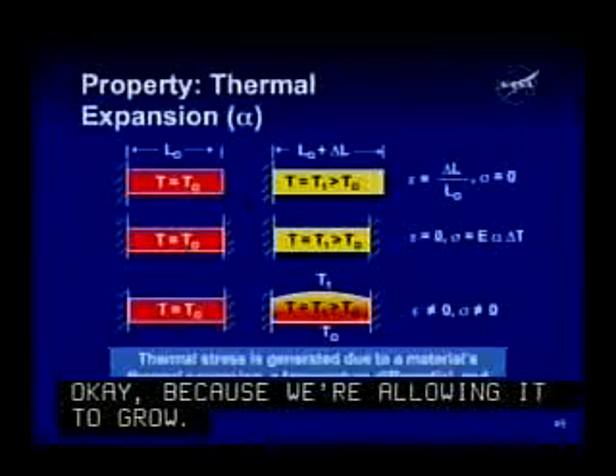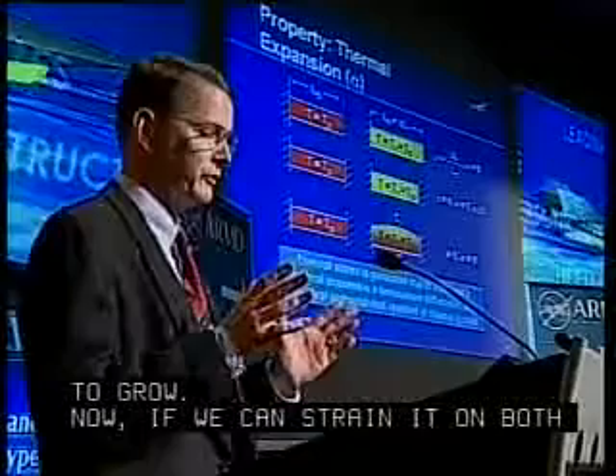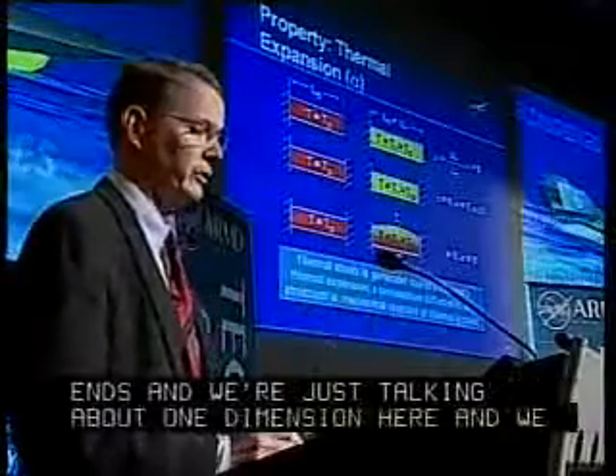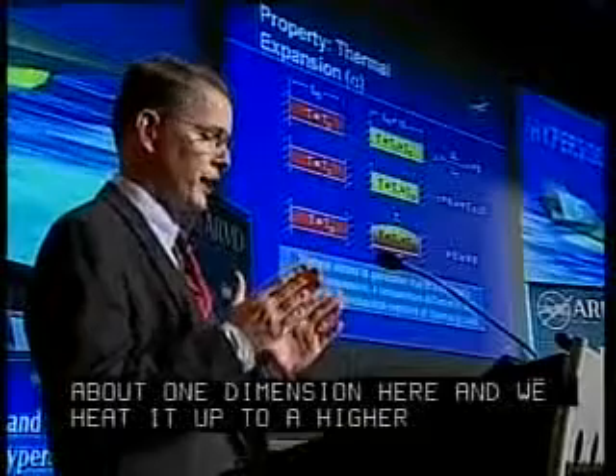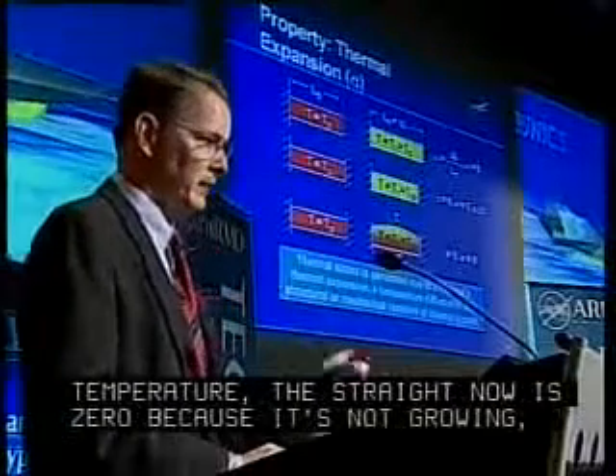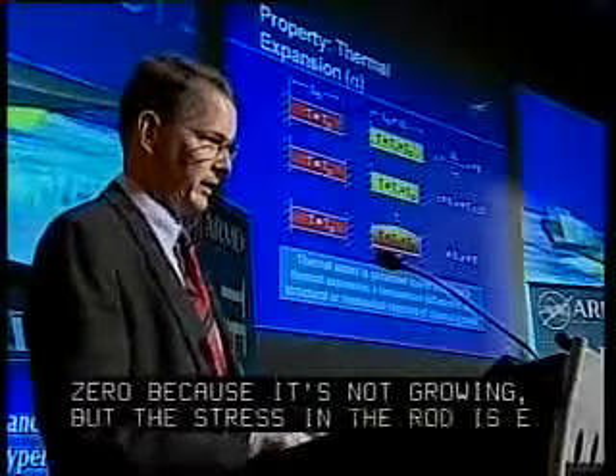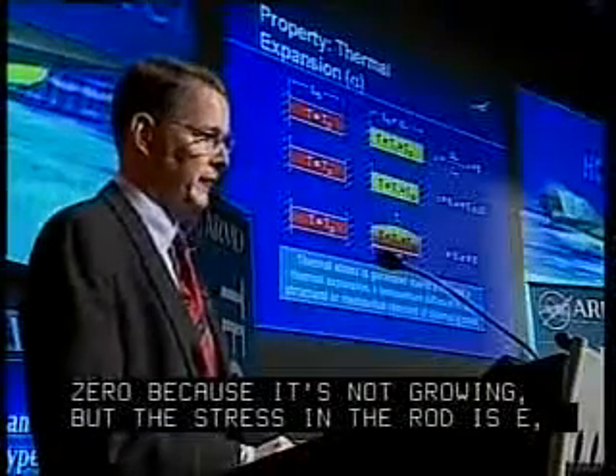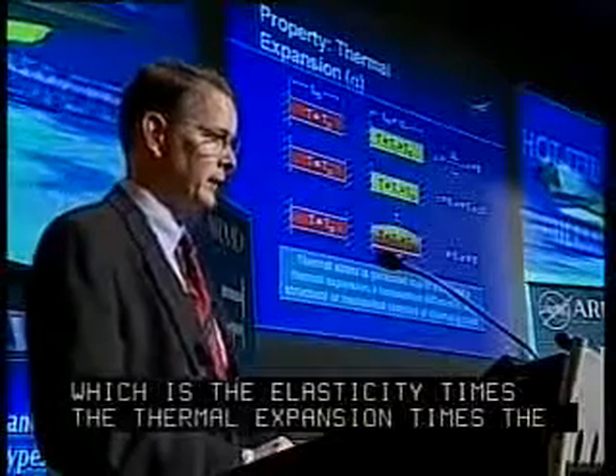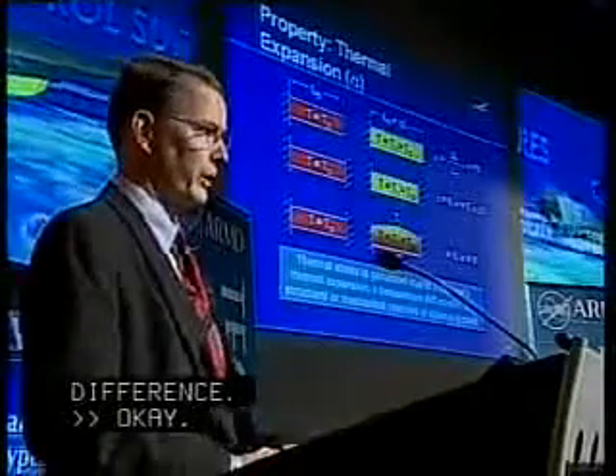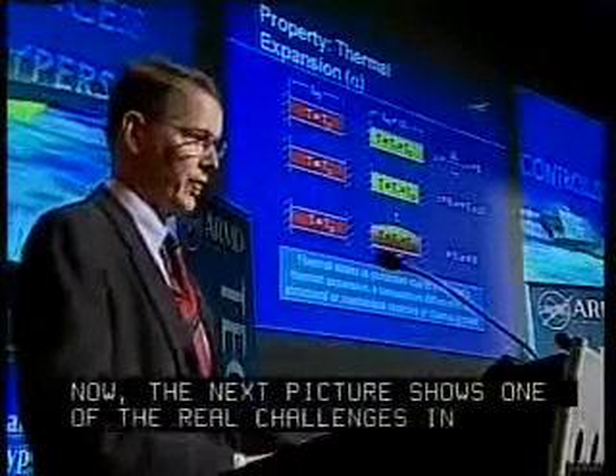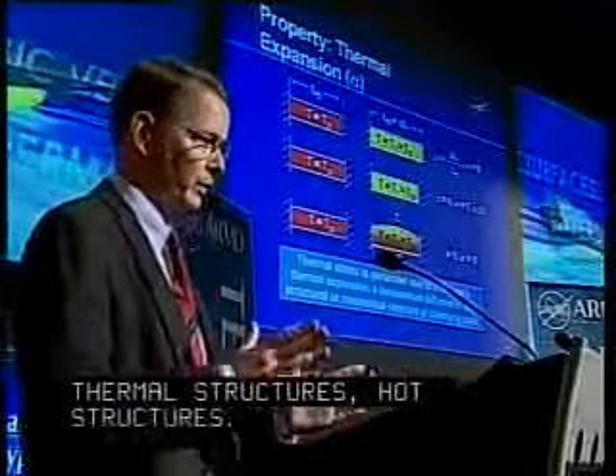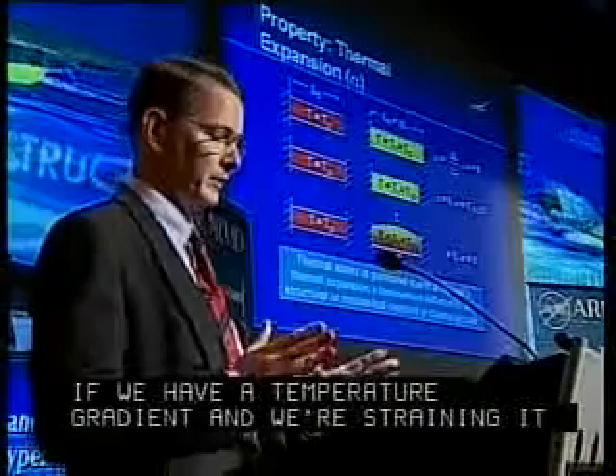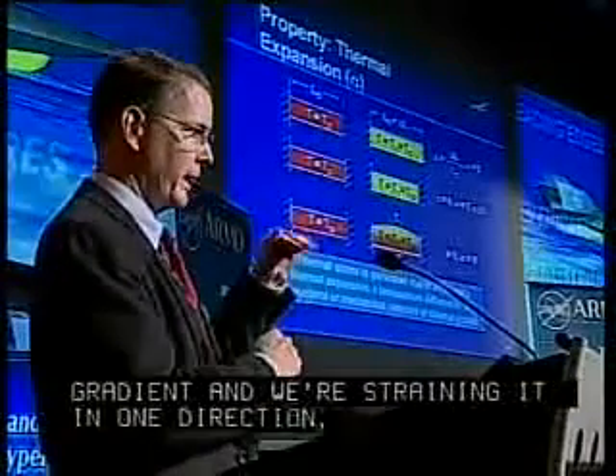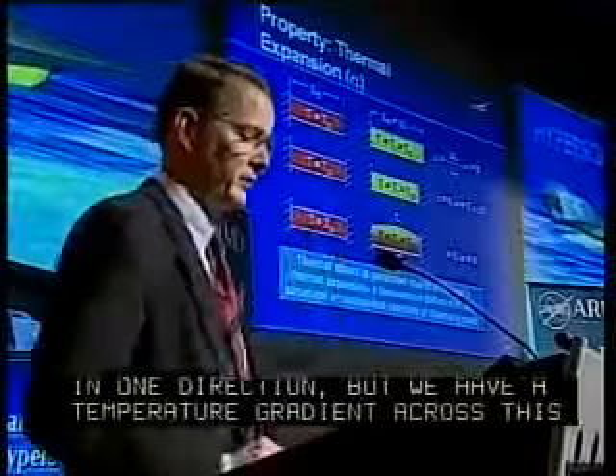Okay, now if we constrain it on both ends, and we're just talking about one dimension here, and we heat it up to a higher temperature, the strain now is 0 because it's not growing, but the stress in the rod is E, which is the modulus of elasticity, times the thermal expansion, times that delta T, that temperature difference. Okay, now the next little pictures show one of the real challenges in thermal structures, hot structures. If we have a temperature gradient, okay, again, we're constraining it in one direction anyway, but we have a temperature gradient across this particular beam.